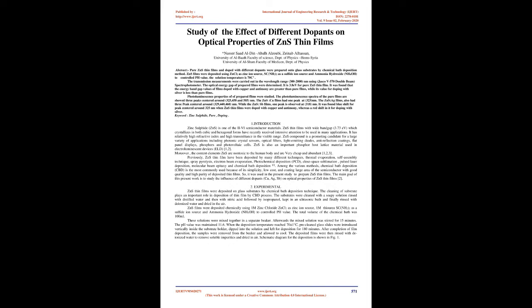It was found blue shift for peaks centered around 325 nm when ZnS thin films were doped with copper and antimony, whereas a red shift in it for doping with silver. Keywords: zinc sulfide, pure, doping.